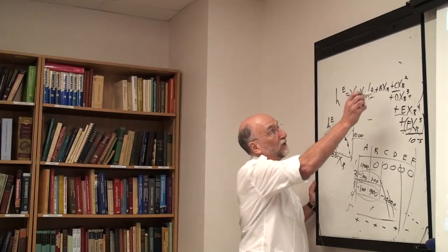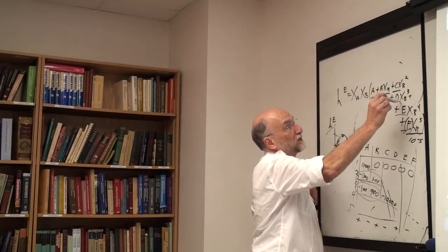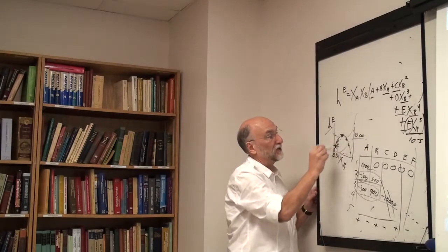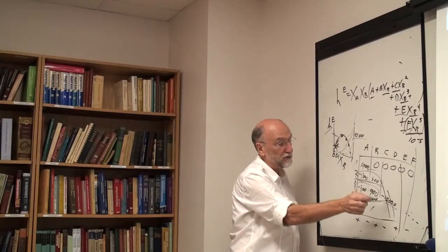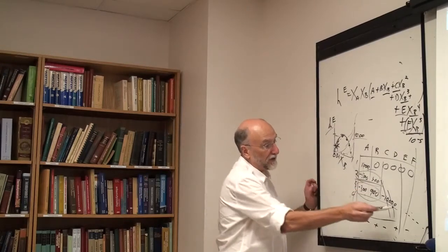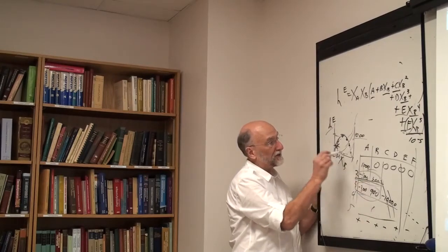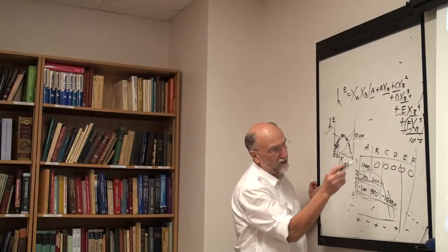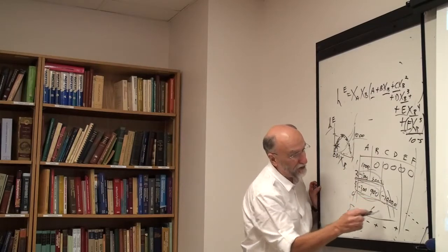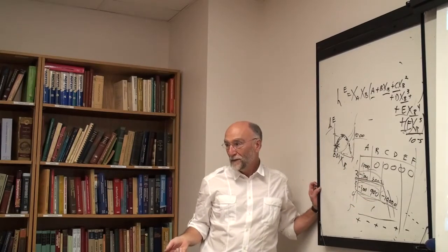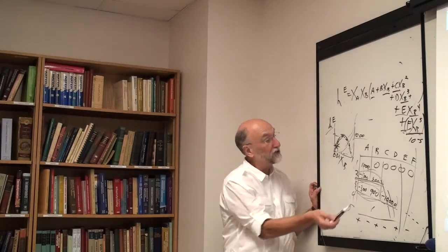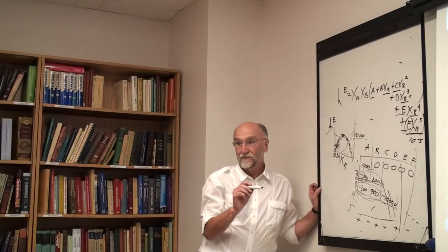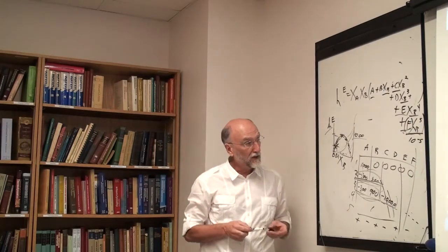And this is because these base functions, xb, xb squared, xb cubed, are very strongly correlated. They all depend very much on composition. So the fit with 3 terms may be very, very similar to the fit with 2 terms, but this isn't evident at all from looking at the coefficients, because the third coefficient is the biggest one numerically. And the first 2 coefficients have changed entirely from what they were before numerically, even though it's almost exactly the same fit. This is because you have correlated terms.